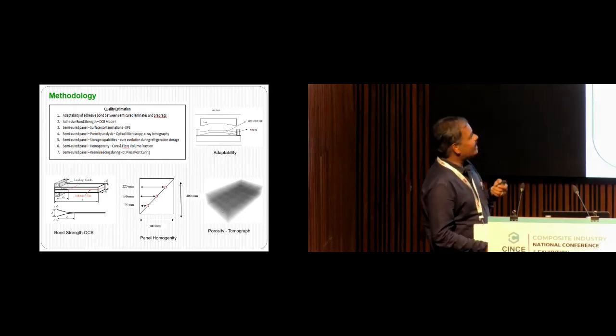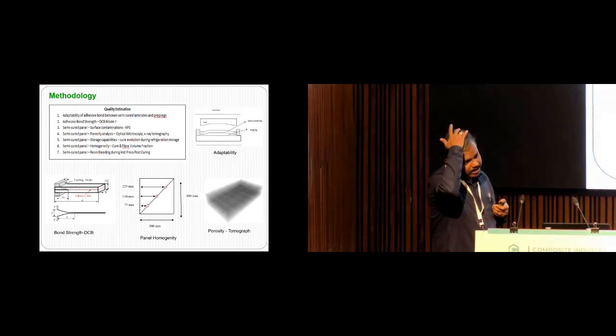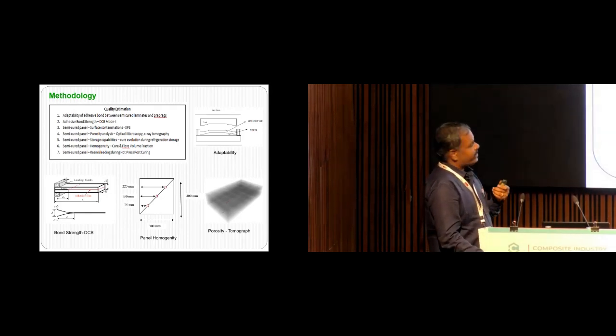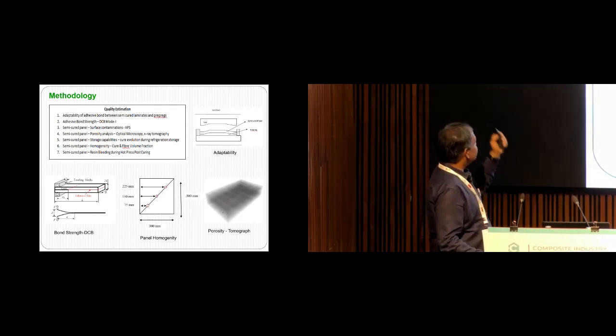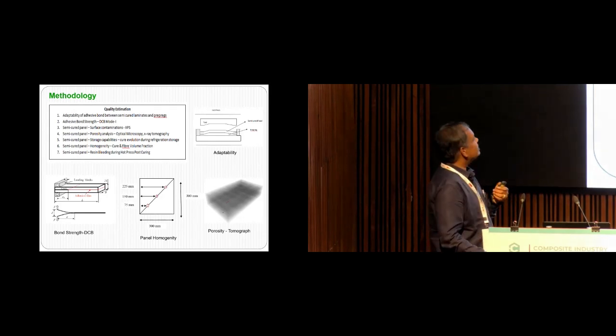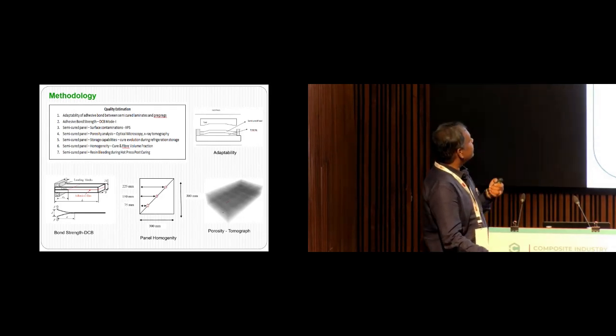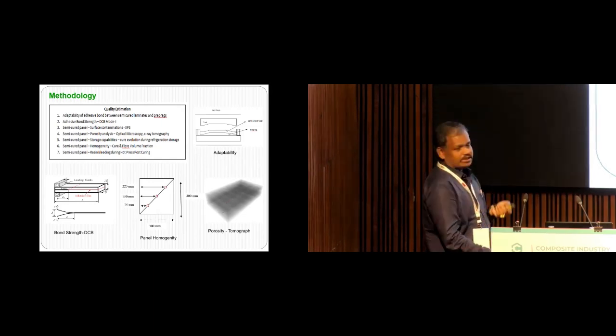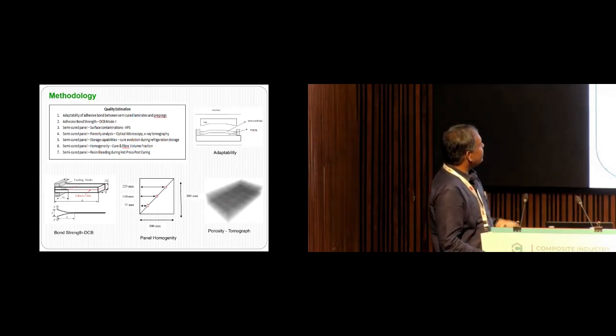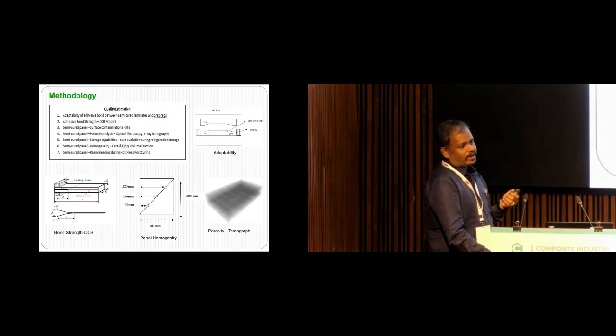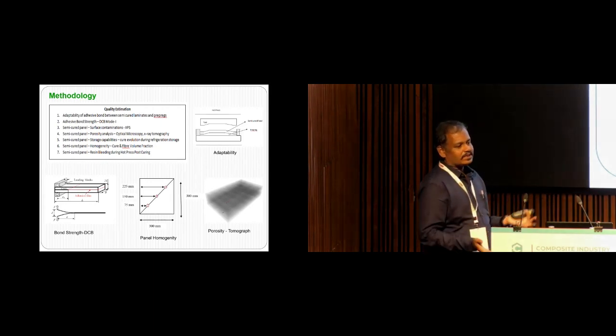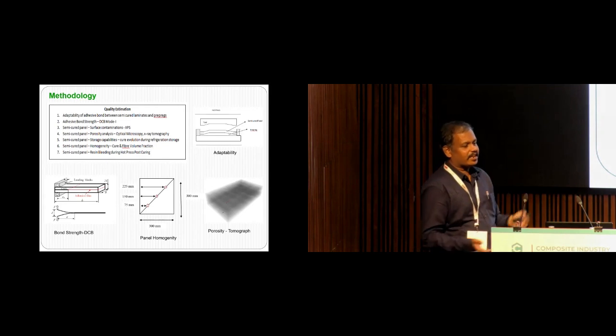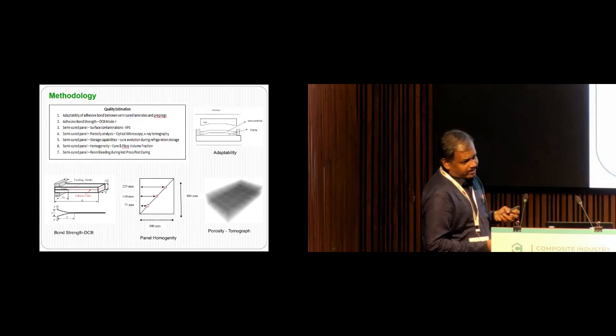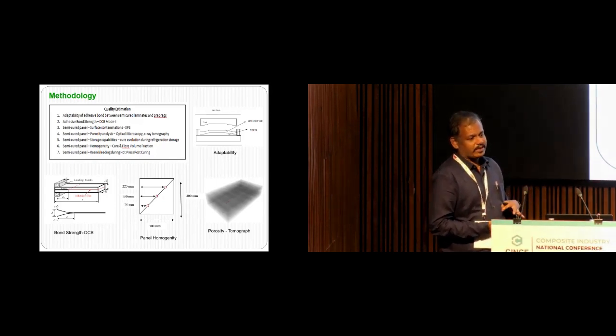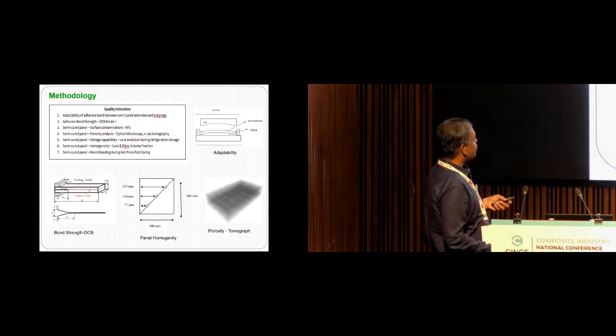When it comes to quality estimation, first of all you have to find out the adhesive bond strength. Next, for the semi-cured panel, which is of our interest, you should check surface contaminations through XPS, and do porosity analysis using optical microscopy and X-ray tomography. Then, I manufacture the semi-cured composite laminate and I can transport it somewhere else and produce the thick section composite laminates in situ. For that I should know the storage capability. How can I store the semi-cured composite laminates?